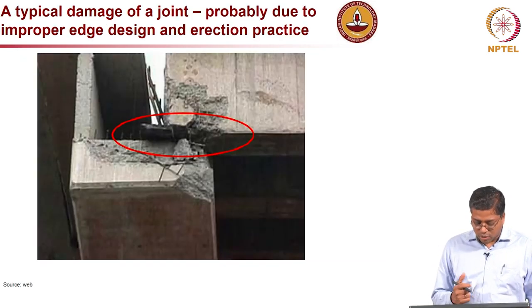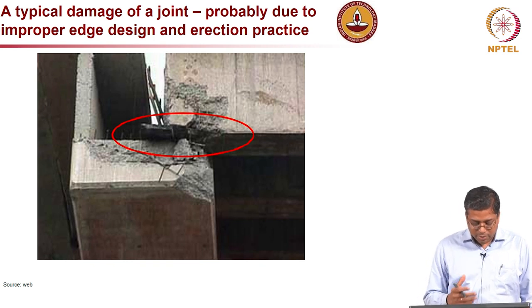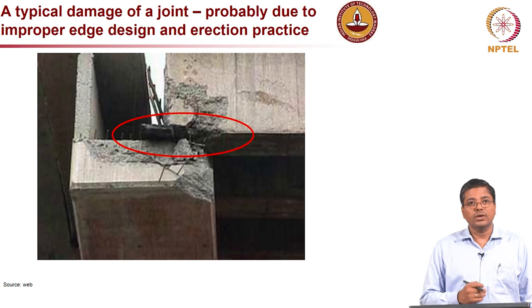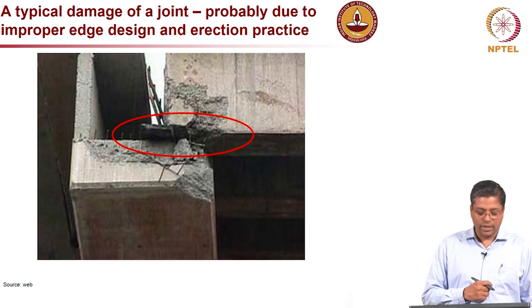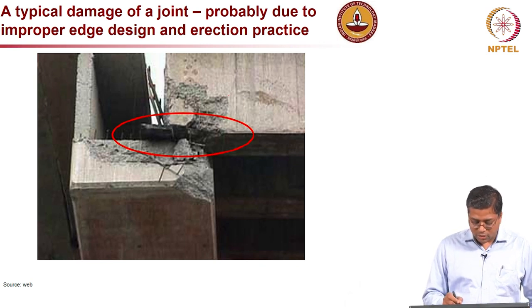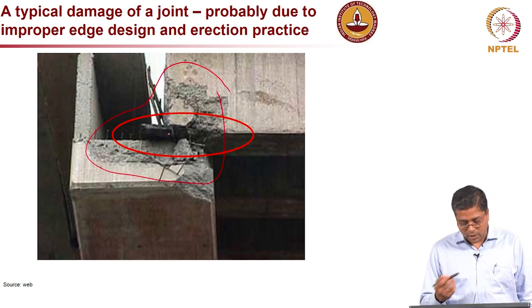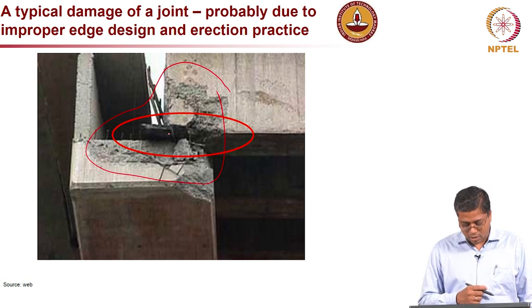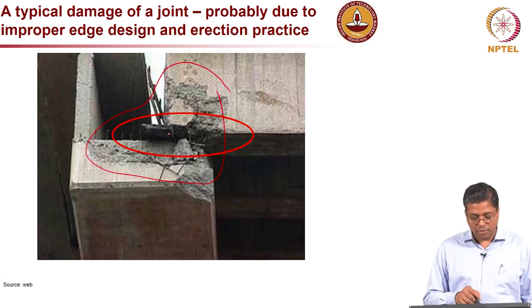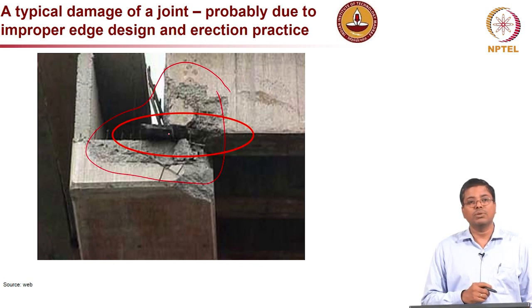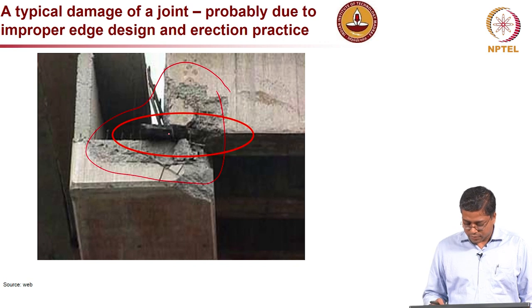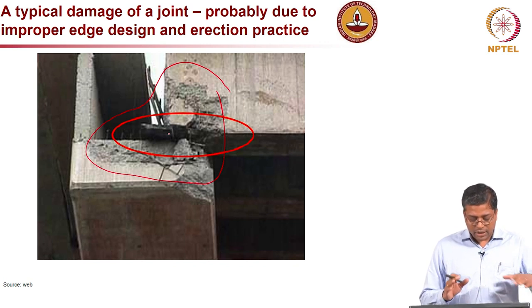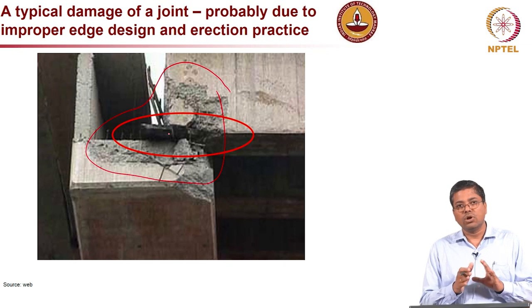Here I just wanted to show you an example where damage has happened because at the time of erection, an impact load can happen, and also because of improper edge design. You can see the damage at the edge, very significant, exposing the reinforcement, which will not look good, but at the same time will also lead to other problems. So erection is also something very important to look at. The element should be erected carefully, and we should not allow any impact load to happen.